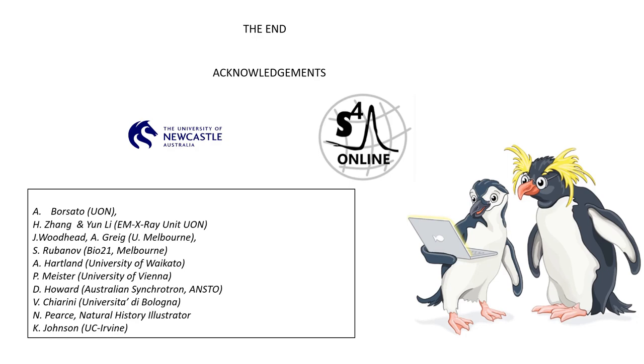You can push. Well, if you have access to a transmission electron microscope and what is called a FIB, so a SEM equipped with a focused ion beam thinner, you just select the fabrics. For example, suppose you have a porous fabric, a columnar porous fabric, you select it. You carve out a FIB section, which is a few micrometers long and a few micrometers deep, but at least you can see the nanoscale. So you can see if you have nanocrystals or not.